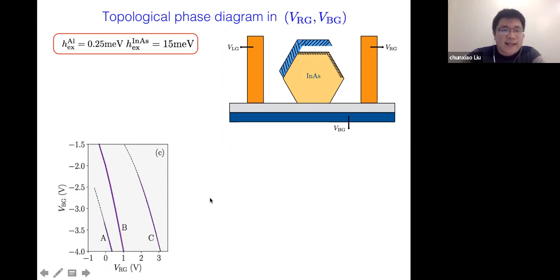And we can see that along these lines, the subband mode can stay topological all the way, as shown in this B. And also the subband mode can undergo topological quantum phase transition, for example, in this A and the C case. This is quite interesting, because in the conventional understanding, when one tunes the gate voltages, it usually changes the chemical potential of the subband mode, leading to topological phase transition. But here in this case, the chemical potential is not changed when you change 2 gates, but still topological phase transition happens. So why is that?